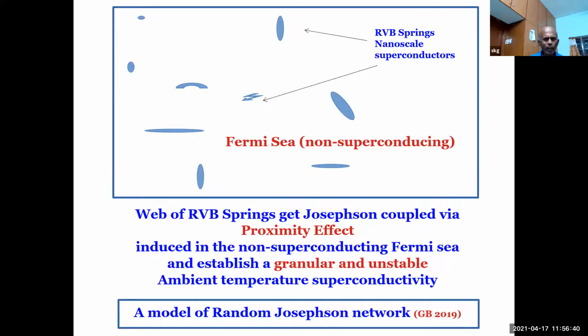So once there is an RVB spring, they can happily connect them through proximity effect. So what you have is some kind of Josephson coupled network. So you can develop a theory using that, and then you get a Tc which is similar to what you see. So this is the model of a random Josephson network. This is my rationalization of this beautiful phenomenon. But of course, when I meet my friends, and I gave a colloquium at Bangalore, I told them that their experiments may turn out to be wrong, but my theory can't be wrong. So of course, they laugh.